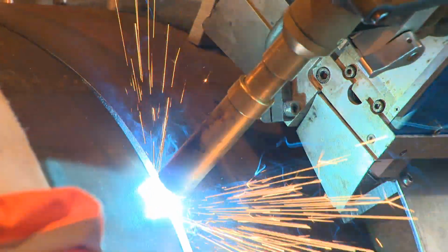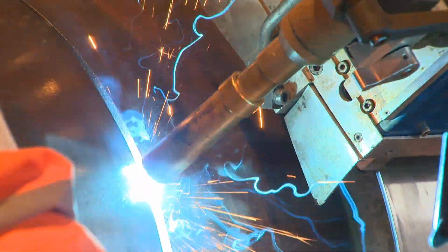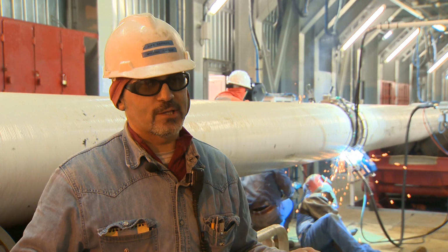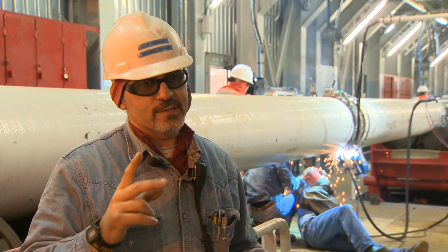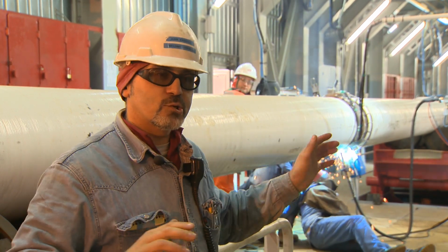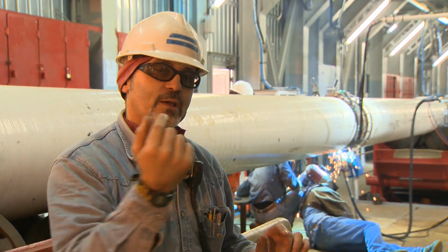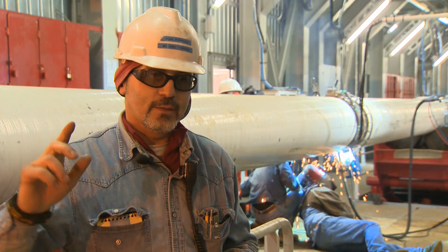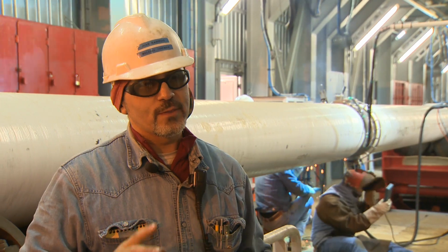The most important operation, welding. We have here 3 welding stations, 3 complete welding stations. The first one is the most difficult because we need to adjust the pipe, make the line up, put together, and then we weld 2 passes, the root pass and hot pass. When we finish, we press the green light, and if all the stations are in green color, the pipe moves to the next station. Then the pipe arrives to station 2, and in station 2, they weld another